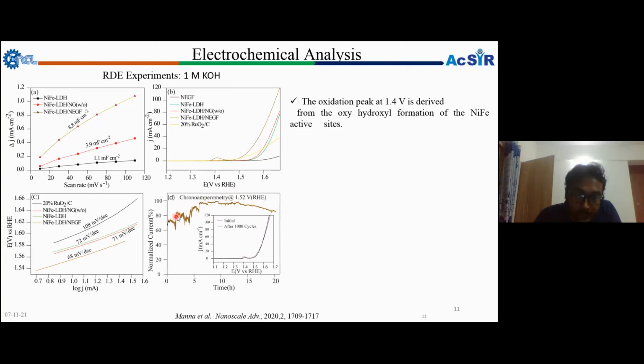But here you can see the noise is coming because, during oxygen evolution, oxygen bubbles form on the rotating electrode. Then after a certain time, when the bubble size is very small, we apply the rotation, so they are removed, and then suddenly the current improves. Up to a certain time there is a surface morphology change, that is a surface roughness change, and after that no noise is coming. Similarly we have done the cyclic voltammetry study for 1000 cycles keeping the same potential window. After 1000 cycles there is no such change in the initial, and after 1000 cycles the LSV plot, which suggests that our catalyst has the best activity as well as durability.